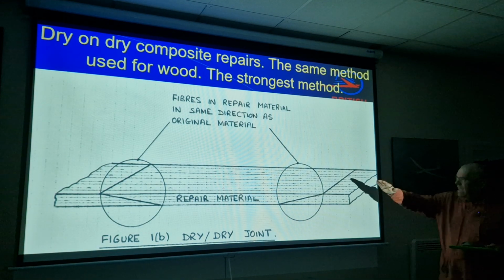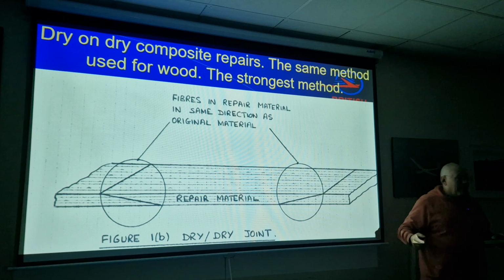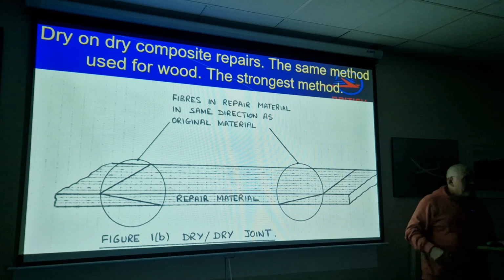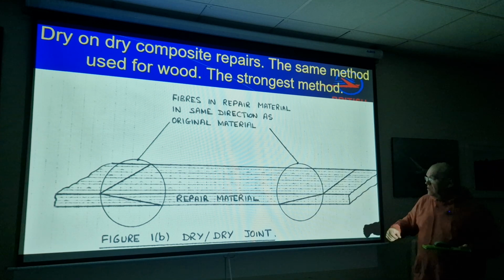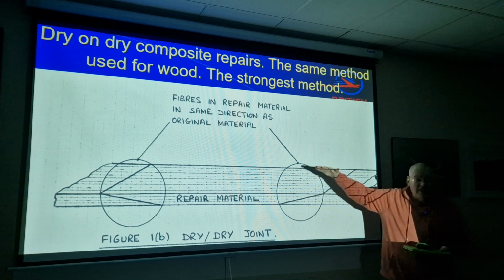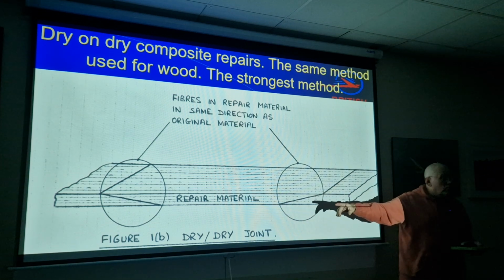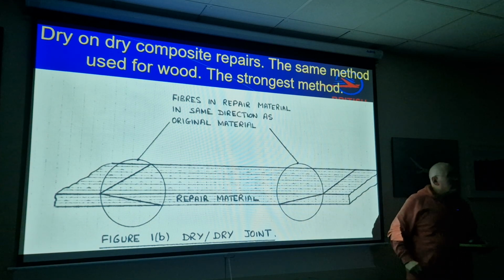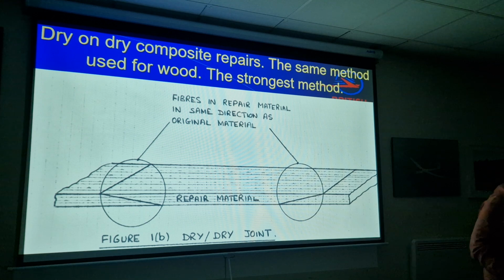rather than just laying material in there, if we treat it as a wood repair, so if we made a spar and did our 100-to-1 splice, or whatever angle we did, and just laid it in there like a bit of wood, what's called a dry-on-dry repair, we were back up to 100% strength. So you literally have to do the same repair scheme in wood as you do in glass fibre or carbon fibre when it comes to main spars. It's the only way you can achieve 100% strength.